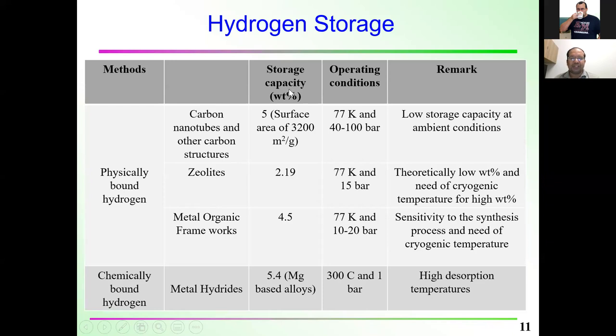We can see here the storage capacity for carbon nanotube or other carbon structures is only 5.8%. If you use zeolite, the storage capacity is 2.198%. Metal organic frameworks have a high storage capacity, but still it's 4.5%. Look at the operating conditions. For carbon nanotube and other carbon nanostructures it is 77 Kelvin, pressure 40 to 100 bar. Zeolite is 77 Kelvin. It's a very low temperature.